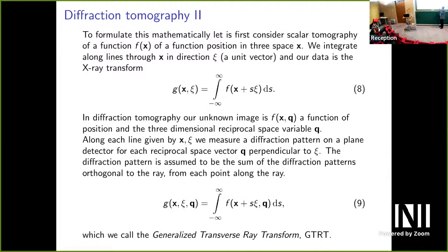And the idea is that this sort of unit of scattering, which is about the width of a beam, can be described by what we might think of as a scattering cross section. In other words, when the beam comes in this direction, then in the Fourier transform variable, what happens is this diffraction pattern. Oh, let me say, the diffraction pattern is captured on the screen, which is two-dimensional. But if you captured all the pictures on the screen, it would be a function of the sphere, right? So we're thinking that each point has a function of the sphere, or the reciprocal space in that.